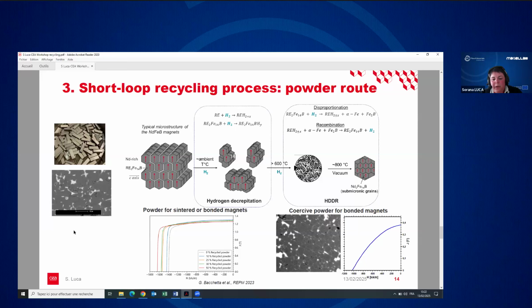These powders will have the same microstructure as the starting material. If we mill down this powder to fine grains, we can manufacture new magnets. Here are some examples of magnets manufactured with different loads of recycled powder. And we can see we obtain good magnetic properties by this process.